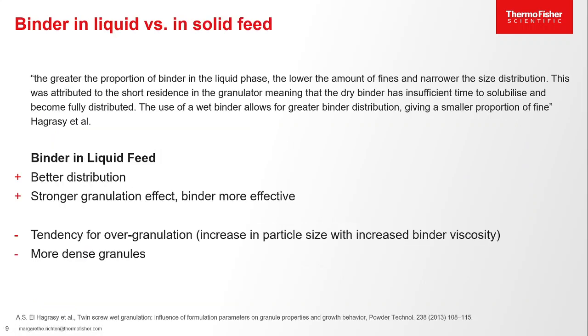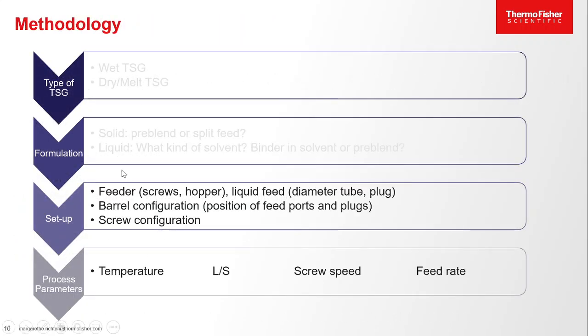And this is a question we have discussed in this slide. There's a little bit more in this publication again, but in a nutshell, you get a better distribution and a stronger granulation effect, so a more effective binder, if you add the binder into the liquid. But you also have the tendency to overgranulate, to make lumps and really large particles and to get quite dense particles.